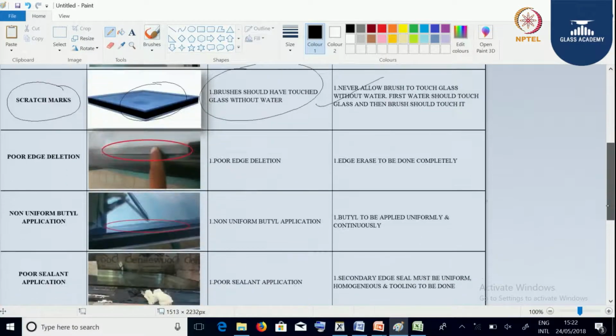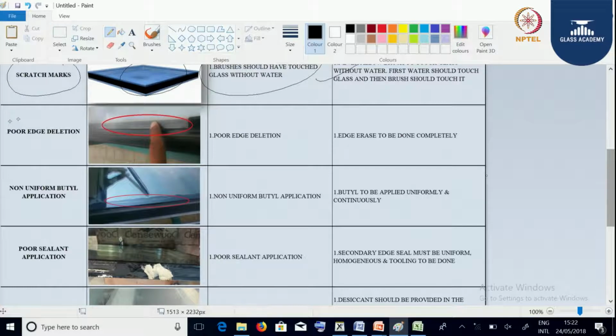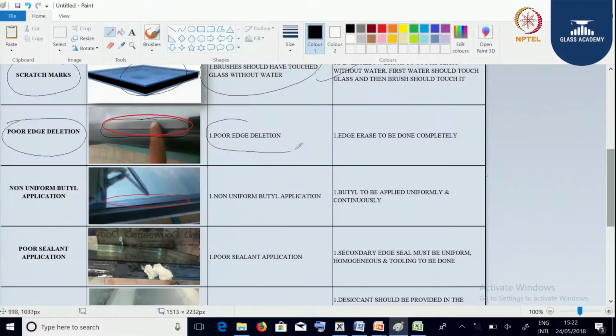Next one is poor edge deletion. You can see in the figure that the edge deletion we have done on the glass is not complete. If there is poor edge deletion, you can see traces of the coating. Our intention is that the coating surface should be completely removed and the surface should be as good as clear glass. This happens because of poor edge deletion, and we can overcome this issue by properly doing the edge deletion with the proper wheel and the proper pressure.